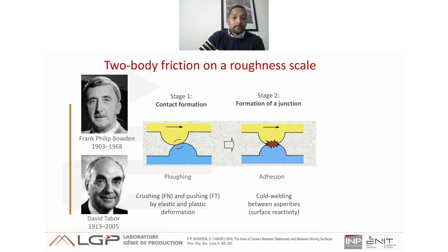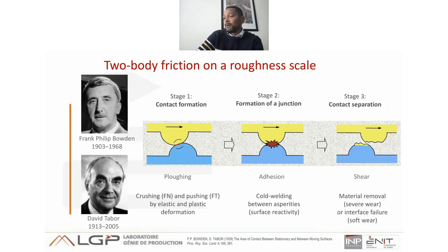Then the second step is the formation of a junction. The atoms approach each other intimately under the effect of the crushing. There is adhesion and cold microwelding between the asperities, which bring into play the reactivity of the surfaces. The third step is the separation of the contact. The movement can only continue by shearing the junction. Shear then occurs, material is torn away, there is sometimes severe wear, or the interface breaks apart.